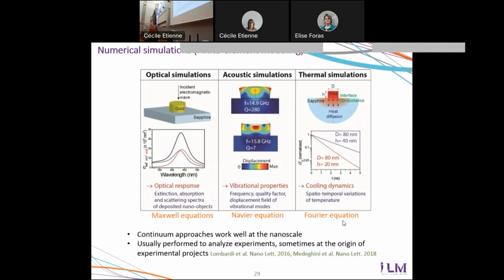Okay, and finally, I want to stress also that apart from these optical characterizations, another tool that is very precious for us, and which is mainly what I'm doing in the group, is to use numerical simulations to characterize the optical properties of our nano objects. So as you have seen, we are using optical techniques which strongly exploit the optical response of metal nano-objects. So we perform a lot of optical simulations in which we compute the optical response of nano-objects in their actual environment of experiments, so including the fact that they are usually deposited on a solid substrate.